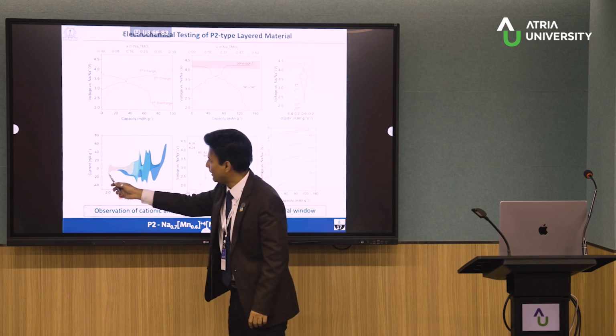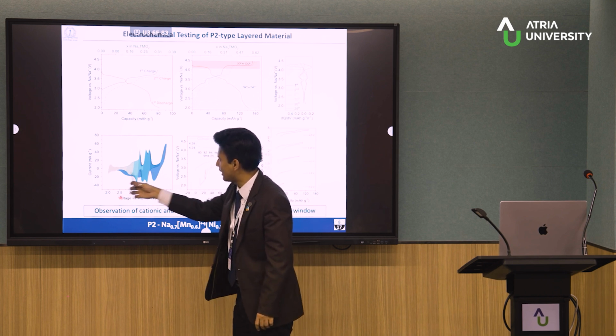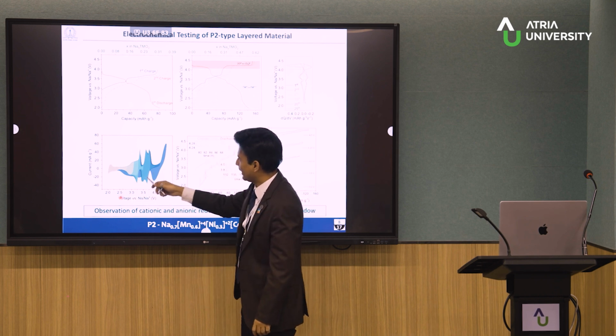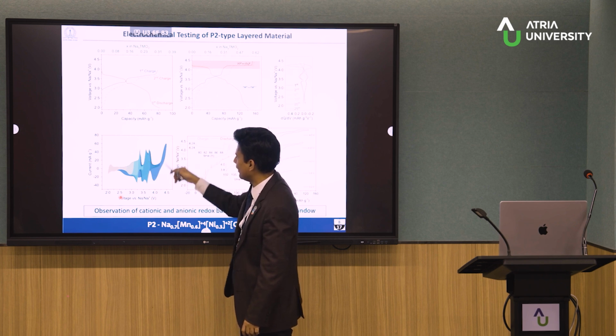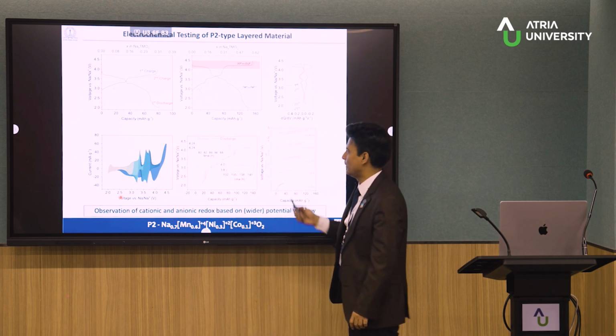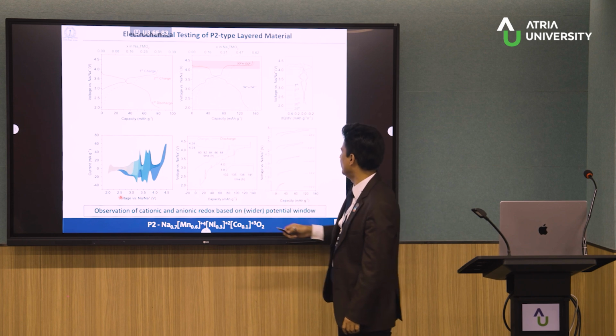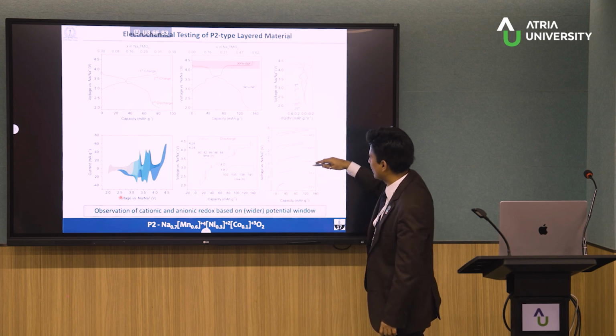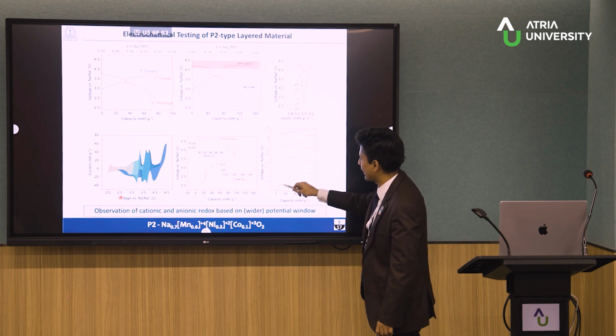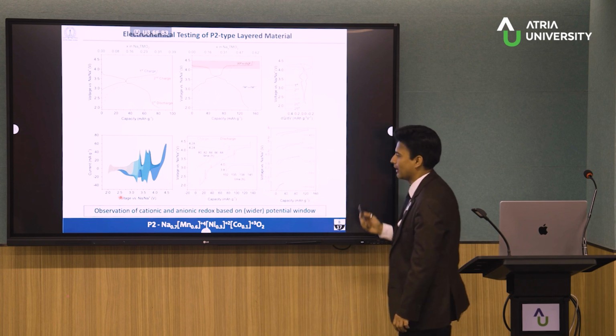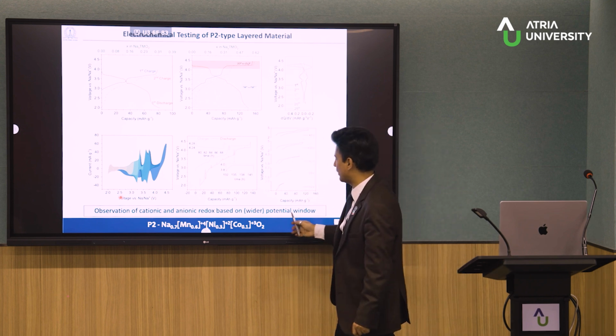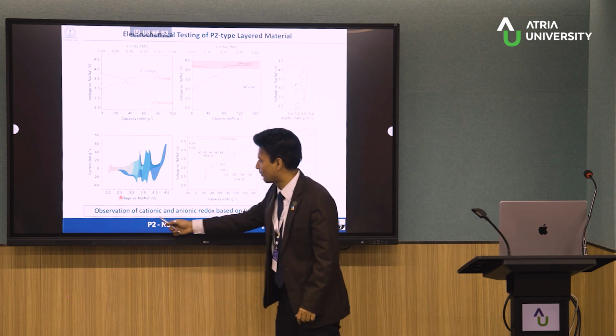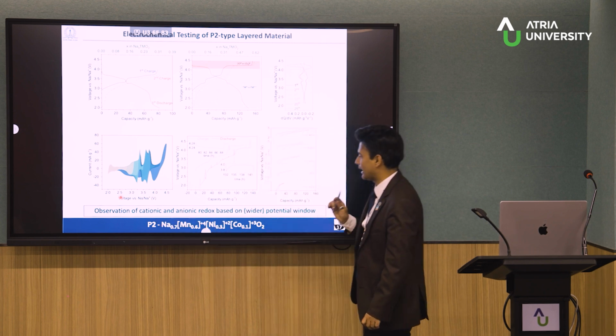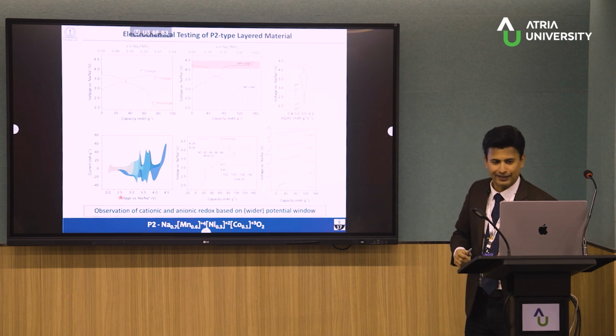Now, this is the dQ/dV curve. If we just sweep the cyclic voltammetry towards higher and higher voltage, later we can actually capture each and everything and the anionic redox also. And also we can see that with GITT and so on. So again, depending on the voltage window, we are getting only cationic or cationic plus anionic. So as a result, we can see with wider potential window, we are getting the observation of both cationic as well as anionic redox to get some high capacity.